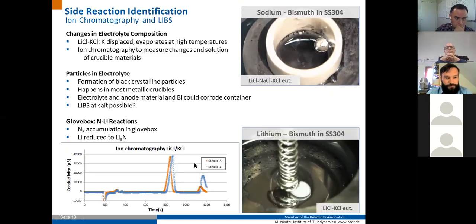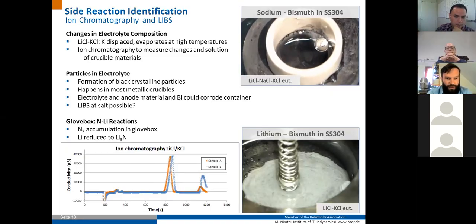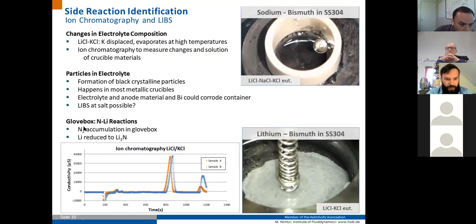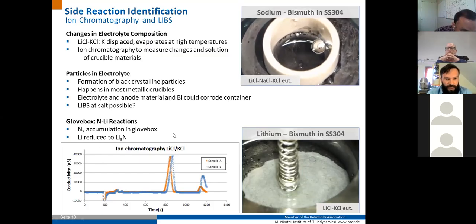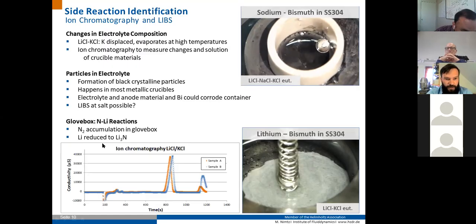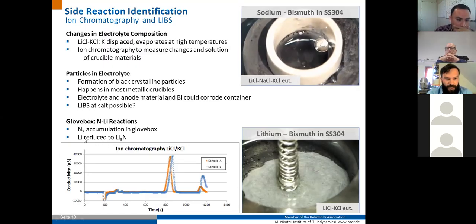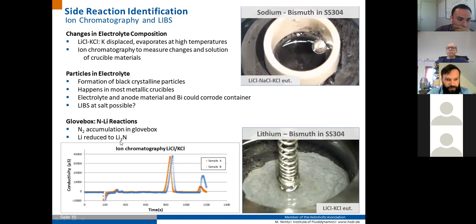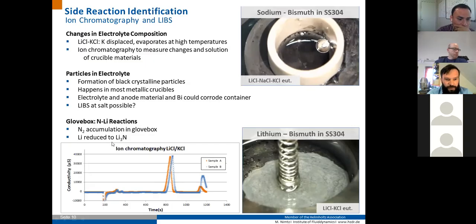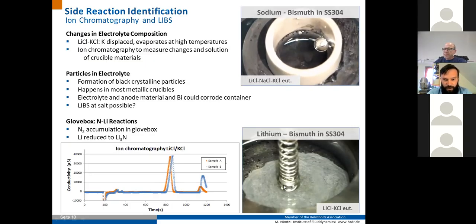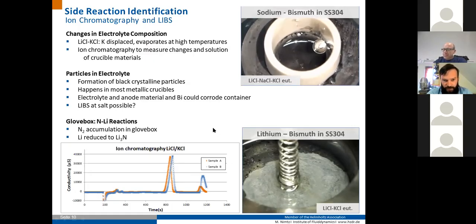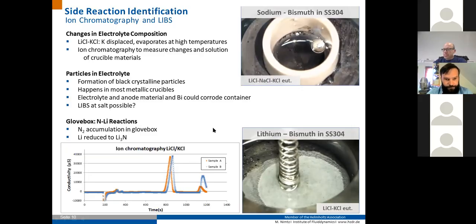Another part, as I mentioned earlier, nitrogen will accumulate in the glove box, and lithium at high temperatures is happily reacting with nitrogen to form lithium nitride, and this will lead to also a slow, we could say, corrosion of the electrode if it's operated in the glove box for a longer time.